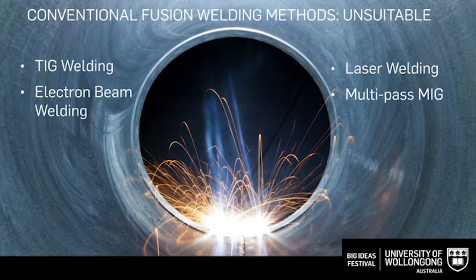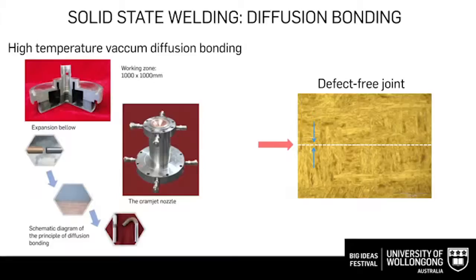The question is, when we build a nuclear reactor, the main method we use is welding — welding all the components together. How can we weld ODS materials? If we use conventional welding methods such as TIG and MIG, or even laser or electron beam, those small particles won't survive in the remelting process. So we must consider different welding methodology. The methodology we are investigating at the moment, we call it the solid-state welding method — we join the materials without melting them.